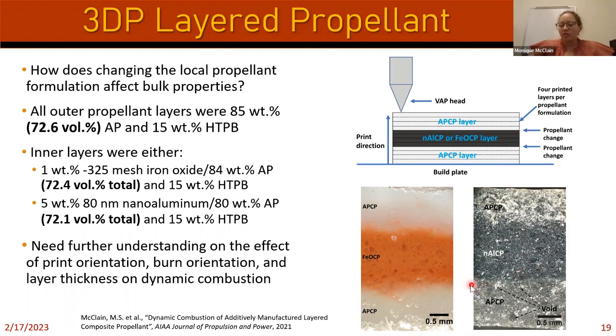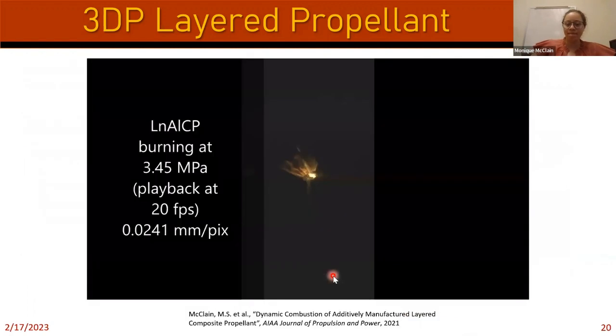Here, for example, that interface is much more defined, and that's probably because the nano-aluminum is stiffer. So that interface will probably be a little better. There won't be as much intermixing. But in general, we're printing multi-material parts at relatively small scales here. So in general, we're trying to understand how changing the propellant composition at small scales will affect how it burns, or maybe even mechanical properties. So I have a video for you showing how it burns.